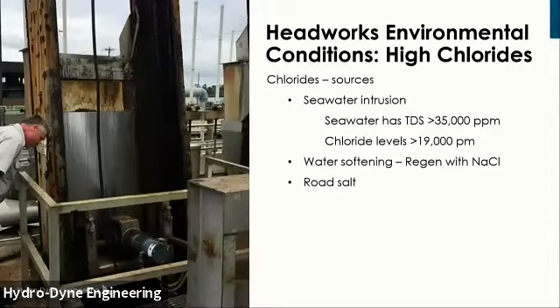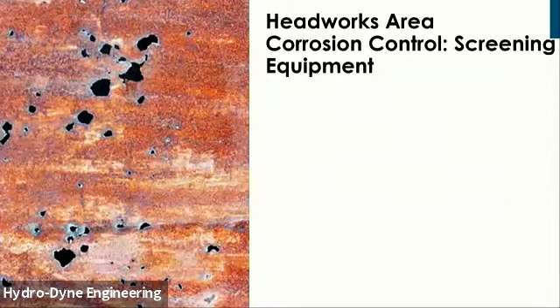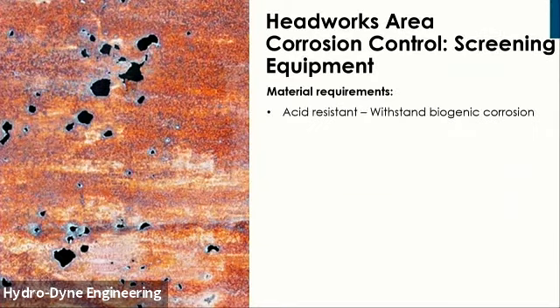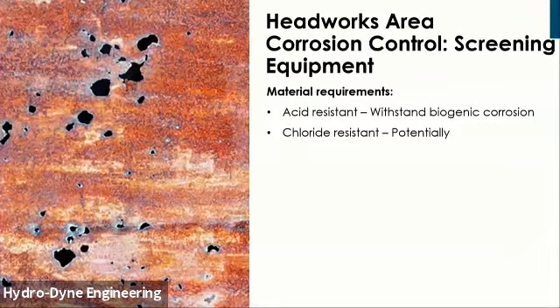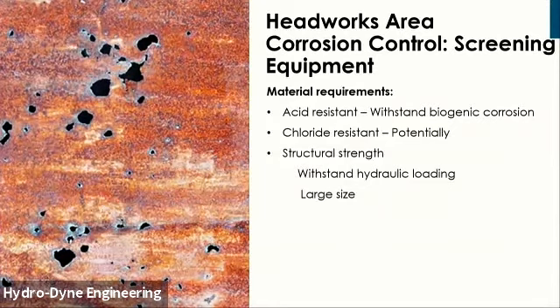Let's go back to the last slide. Here's a good example. It's not our screen, but you can see the pitting caused. This is a coastal screen, and we have pitting caused in the stainless steel by chlorides as they're entrained in air. And we don't want the rust on the screens. Let's talk about requirements. For screening equipment, we need acid-resistant materials. We need materials that can withstand biogenic corrosion. We have to have chloride-resistant materials potentially. We have to have materials with structural strength. They have to withstand hydraulic loading and potentially be very large sizes. So whatever material we pick has to hold up for a long time. We typically build equipment with a 20-year lifespan.